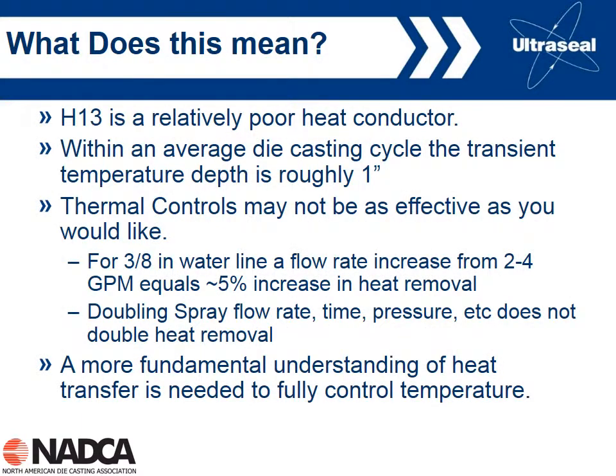So what does this mean? What this means is that H13, as we know, is a relatively poor conductor of heat. And so within the average die casting cycle, 60 seconds or so, the transient temperature depth is about 1 inch or so. So thermal controls may not be as effective as we'd like, or maybe as we think.